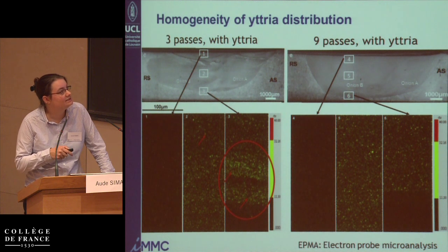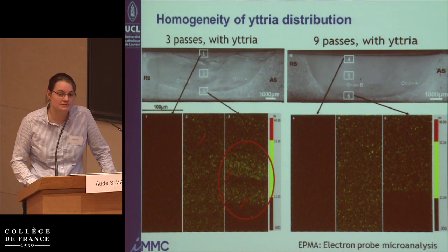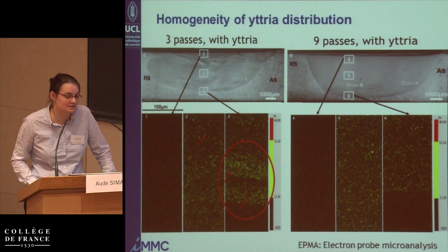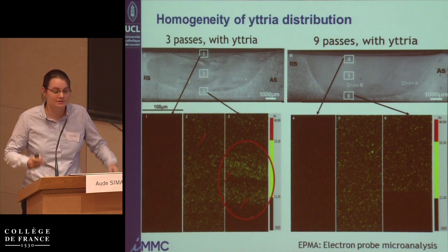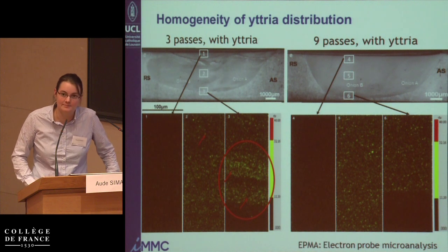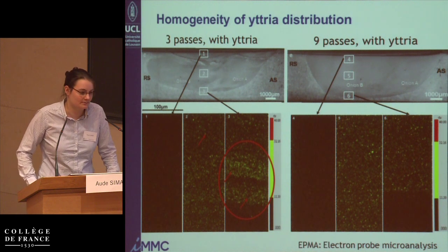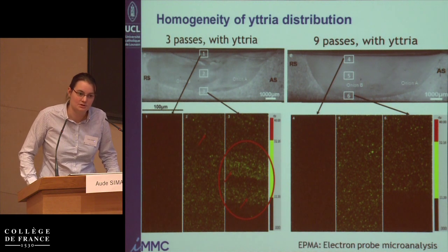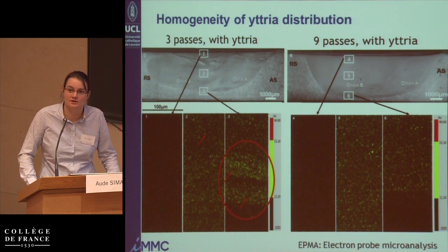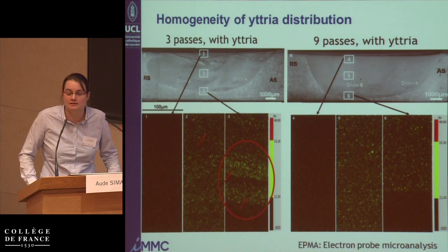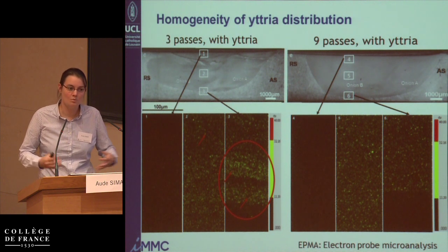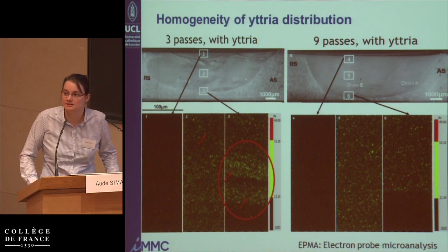You can already see it macroscopically, but when you look at the yttrium oxide distribution, the microscopic distribution is much better after 9 passes. So we'll keep on working with samples with 9 passes. That's quite demanding, because it means that making one material is still long.